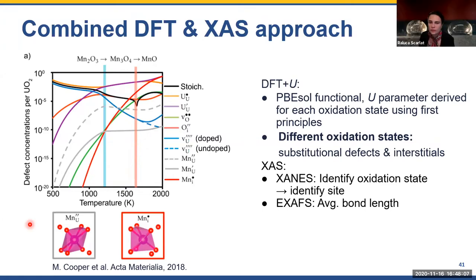I see. So a similar mechanism then might be valid here too with manganese. Exactly. Because we have different oxidation states that are possible with manganese, the computational methods at the moment predict that manganese would be even more powerful, or would enable the growth of even larger grains. The problem we are having experimentally is that manganese volatilizes at even lower temperatures than chromium does.